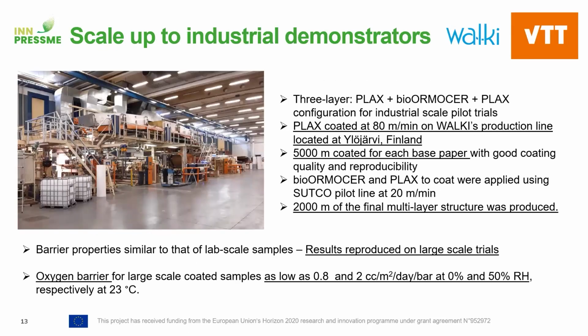Then we moved with these two trial points, the three-layer structure PLAX, bioORMOCER, PLAX, coated on both of these base papers. We did this on Walki's industrial pilot line. The PLAX was coated at Walki, Ylöjärvi, and we got up to 5000 meters of coating applied, so we could go to very large scales. After that the paper was sent back to VTT, where we coated the bioORMOCER and PLAX, and the final material was 2,000 meters of multi-layer material. These also had very similar barrier properties and an even enhanced oxygen barrier compared to the lab scale experiments.